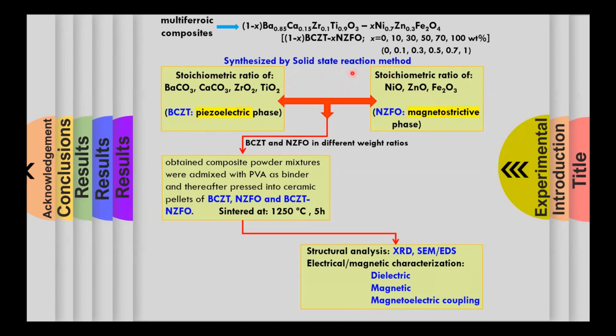So BCZT powder and nickel zinc ferrite powder were prepared separately using the stoichiometric ratio of their respective metal carbonates and oxides. And then the nickel zinc ferrite powder was added into the BCZT in different weight ratios: 10, 30, 50, 70. After mixing the two, the powders were pelletized and sintered, and the obtained samples were characterized for their structural, microstructural, electrical, magnetic, and magnetoelectric properties.